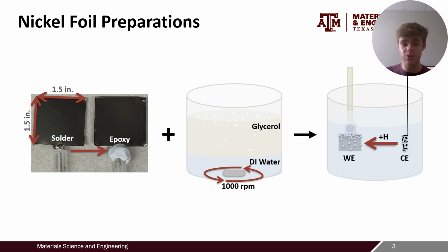So the foils were charged in these electrolytes for times ranging between 0 and 30 hours at a 600 millivolt overpotential using a 3-electrode cell setup with the sample as the working electrode. So that's shown on the right here, where the counter electrode provides the hydrogen, which goes into the working electrode, which is the nickel foil.